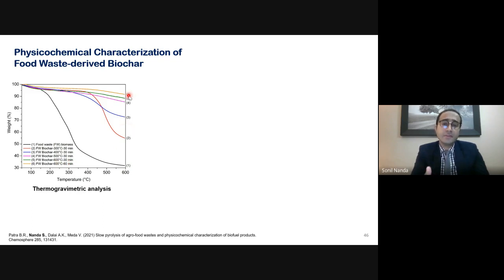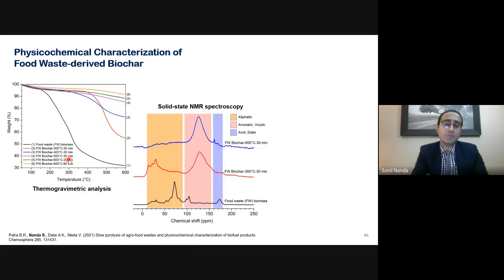As we increase the severity of the pyrolysis, which means when we keep on increasing the temperature and reaction time, you can see that the biochar tends to be more thermally stable and shows very little weight loss. It starts from 100% and the weight loss finishes somewhere around 95%, which shows only 5% weight loss for the biochars which are produced at extremely high temperatures and long reaction times. This indicates that the biochar produced at high temperature and longer reaction time are thermally stable because of different aromatization properties or increase in the concentration of carbon-carbon single and double bonds.